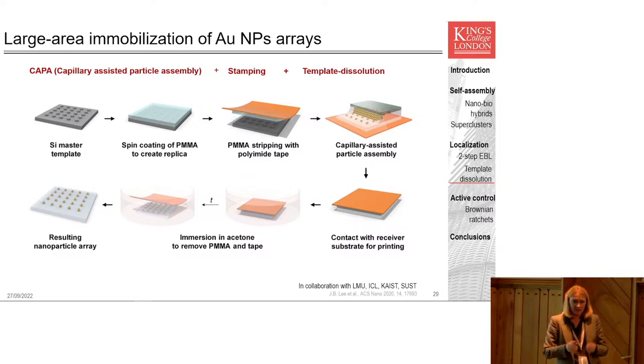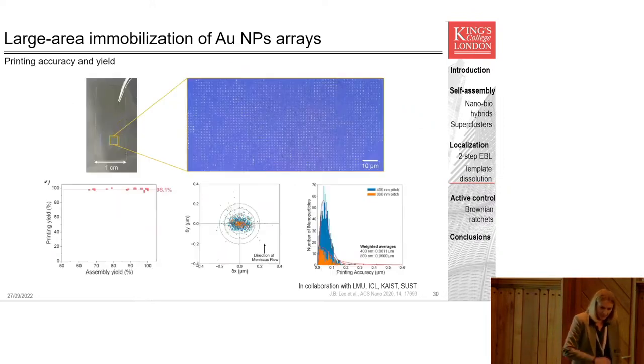Of course, here you get an interplay between the forces between the nanoparticle and the substrate and the forces between the nanoparticle and the solvent. So if the latter are stronger, the particles will lift off, but if you manage to print them strongly enough, then they will remain on the substrate. And using this method, you can really print very, very large arrays of nanoparticles. So these are 100 nanometer nanoparticles spaced, I think, about 2 microns away from each other over a very large area, with printing yields of about 98% and accuracy of about 60 nanometers in location.